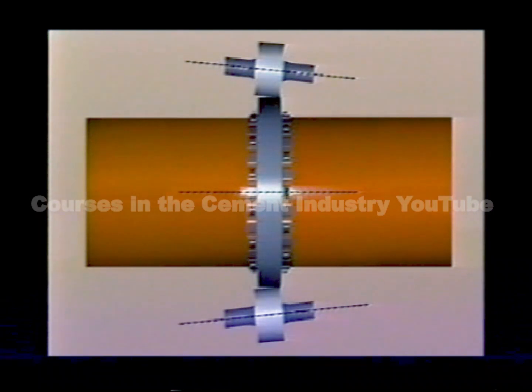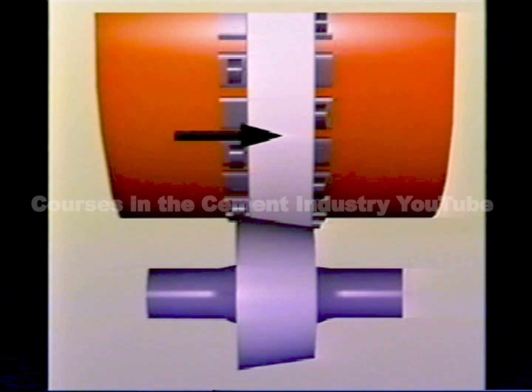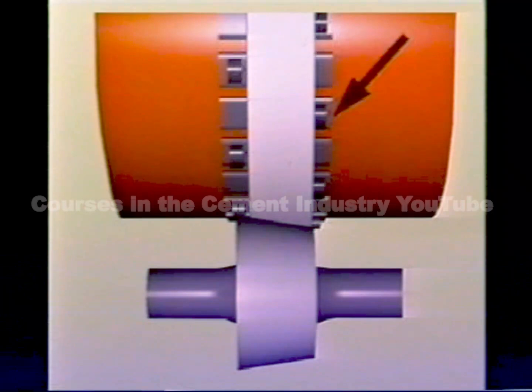The second wear problem, tapered tires and rollers, occurs when rollers are misadjusted or skewed so their axis of rotation are no longer parallel to the kiln. As a result, the tire or roller diameter becomes slightly smaller on one side. The surface load is not properly distributed, and the tire tends to shift toward the side of the smaller roller diameter. This shift can result in premature bearing failure and put undue stress on the stop blocks and support pads, causing excessive wear and cracked welds.